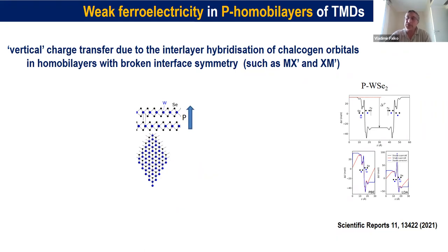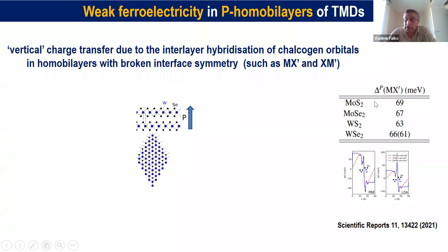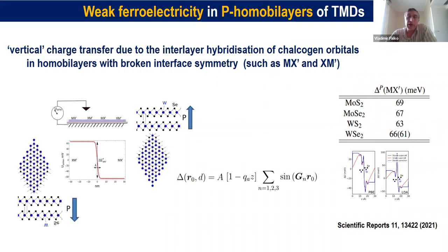and with density functional theory, and also the potential of the double charge layer, which here is identified as parameter delta. So when we calculated it for various TMDs, we got numbers between 60 to 70 millielectron volts. And this quantity is actually measurable because if you scan the surface of the bilayer placed on top of a metallic plate with a metallic tip that measures local potential, then in Kelvin probe microscopy, you would start seeing potential steps of twice this delta when you cross the border between consecutive domains, which are mirror images of each other, and therefore they have the opposite direction of the out-of-plane electric polarization.